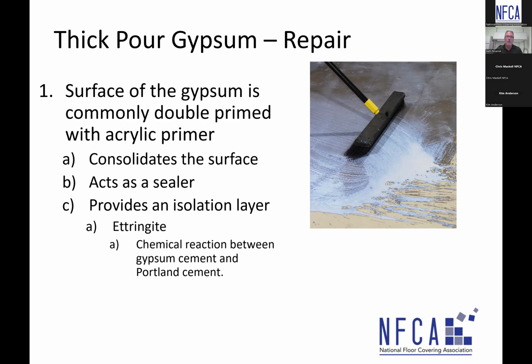So while I said that Portland cement itself has a little teeny bit of gypsum to help regulate set, if we have a pure gypsum material and we have a pure Portland cement material that are interfaced with each other, the chemical reaction of the Portland cement with the water molecule can have an adverse reaction with the existing gypsum and create what they call ettringite.